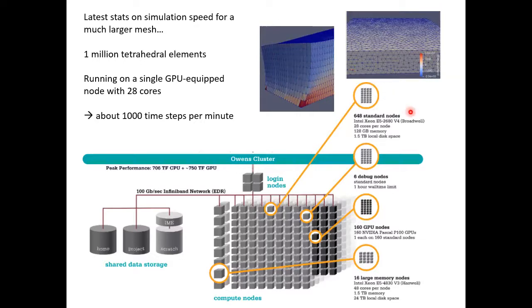The disordered mesh we typically use, even though I'm a real DIY person in general, I don't insist on doing everything myself. We did use some meshing software developed by other people that is optimized in various ways that maybe would be better than what we could do brute force on our own. But what you can see is that this particular one, it's a few elements thick. But if we have very, very thin films, we have to mesh down pretty small. And then we have a very fine mesh, and the code can run kind of slow. So we have to be careful about the aspect ratio of the things we're trying to model.